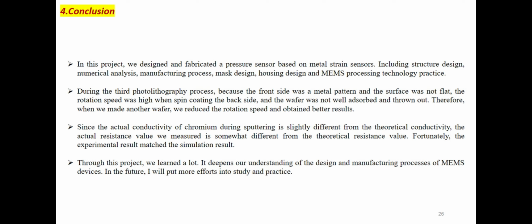Since the actual conductivity of the chromium during sputtering is slightly different from the theoretical conductivity, the actual resistance value we measured is somewhat different from the theoretical resistance value. Fortunately, the experimental result matched the simulation result.